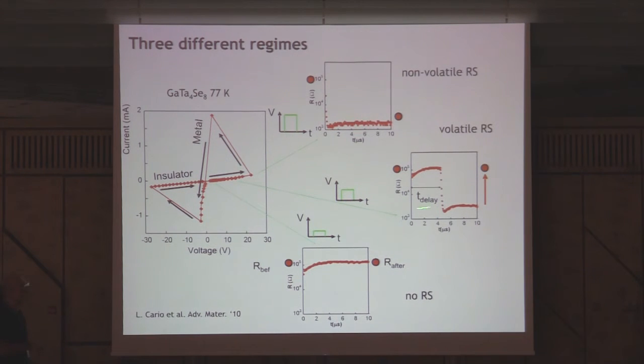So this is intrinsic behavior, and one way to think about that, you can think of this as being like in an elastic regime. So this would be an elastic regime, like a spring. It comes back exactly to the same situation, but this is more plastic. So it's like you have a paper clip that you can just wind when you're bored, and then you unwind, and it almost gets back to the same situation, but it's not quite the same. So there you are introducing defects or whatever. In any case, this is plastic, and this is elastic, and very well reproducible.